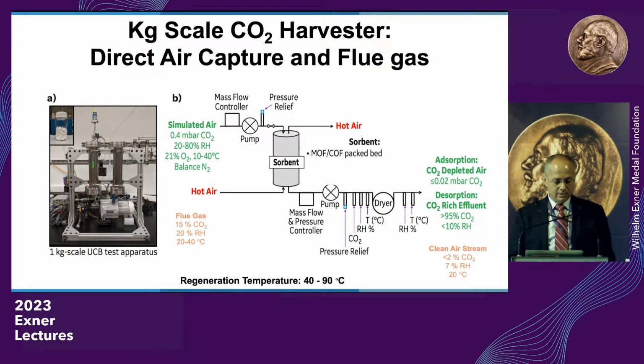Here's a flue gas. When it's 15% CO2, this is conditions of flue gas, and you can reduce the flue gas from 15% CO2 to less than 2% CO2. So we think that this is a very important illustration that MOFs work for carbon capture. Okay, there are many things that we have to do. We have to scale it up to more than a kilogram quantity, which shouldn't be hard. We were scaling MOFs with BASF to multi-ton quantities. And we have to show that, in fact, this can do many cycles, up to 100,000 cycles. Okay, that's basically what the requirement would be.